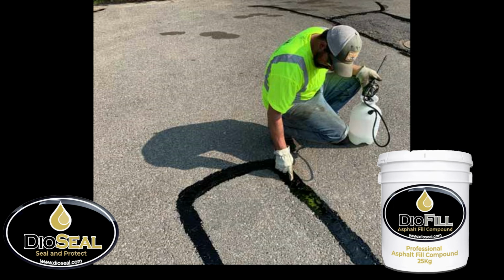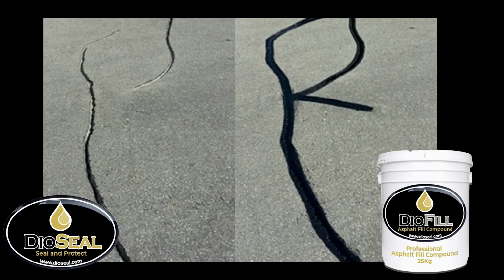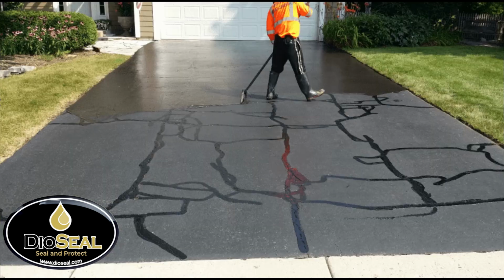Designed to be used in conjunction with DioSeal Sealcoat, DioFill asphalt repair compound effectively fills and repairs areas that can become susceptible to allow water to penetrate the substrate, leading to breakdown damage of the asphalt. Any loose asphalt is removed from the area ready to accept DioFill asphalt repair compound. DioFill is a specially formulated combination of bitumen emulsion modified with an elastomer which together forms a tough and long-lasting barrier against the entry of water. DioFill has excellent adhesive properties and can even be applied to damp surfaces.